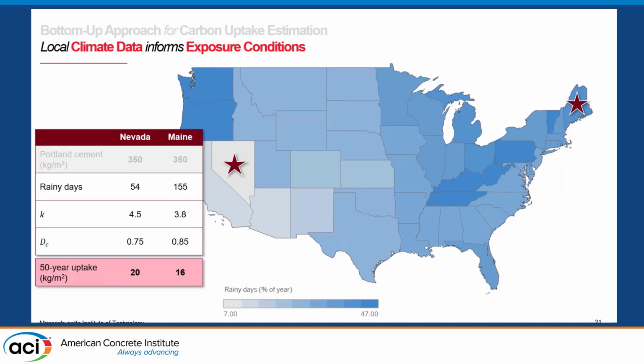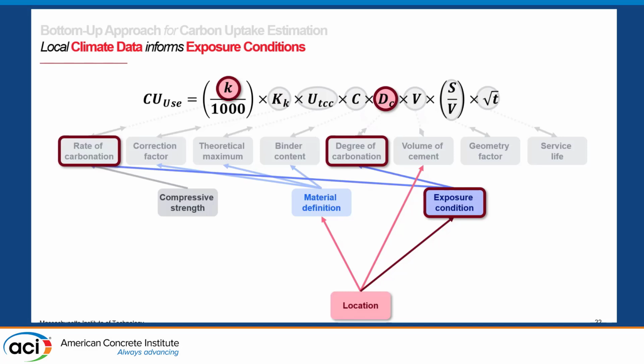Yeah, so what we see is the climate affects both the rate of carbonation K, as the drier location has a higher rate of carbonation, and it also affects the degree of carbonation, the DC factor there, as the rainier state actually has the higher degree of carbonation. Accounting for both of these factors together, in this example, we see that in the drier location, there's a higher 50-year uptake potential per meter square of concrete surfaces exposed. So the breakdown of outdoor exposure conditions also affect carbon uptake.